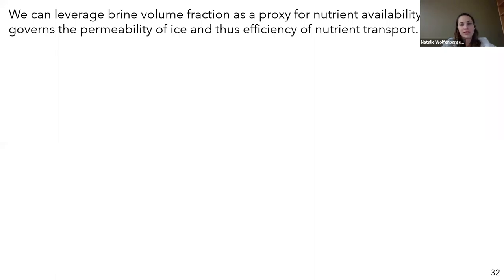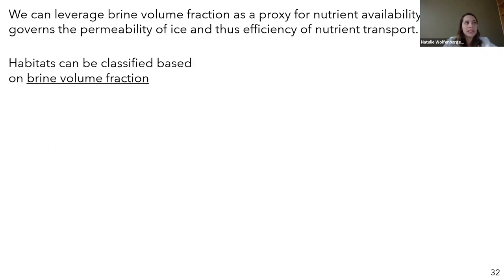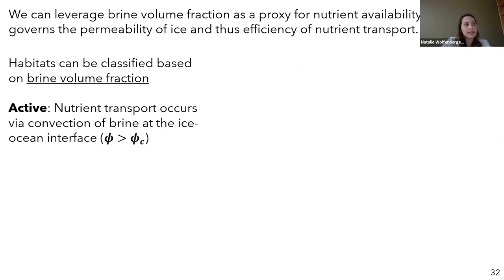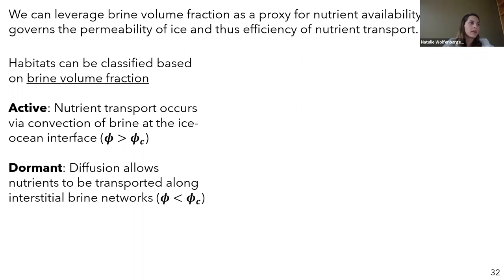So instead of using these metabolic rates, I decided to take the perspective of looking at efficiency of nutrient transport itself in terms of the permeability of ice. And going back to our previous discussion, we had noted that the permeability of ice seems to drop off at this percolation threshold. So essentially what I decided to do is classify habitats based on brine volume fraction, where active habitats represent the region where nutrient transport can occur via convection of the brine and exchange of seawater at the ice-ocean interface. And so this is characterized by a brine volume fraction above this critical porosity.